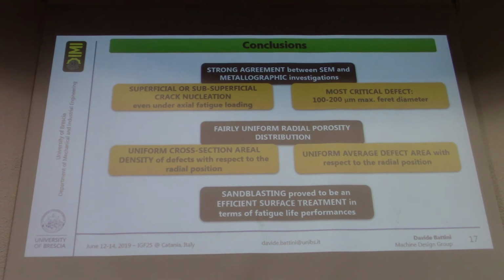So in conclusion, we got pretty happy with our experiments, even though it's still a work in progress, since we got a good agreement between defect analysis on metallographic images and SEM analysis. And we found out that it seems that there is a radially uniform distribution of the porosities, which is kind of strange since the current literature doesn't really talk about it, and it only focuses on the fact that additive manufactured specimens show a lot more defects in the outer region of the specimens.